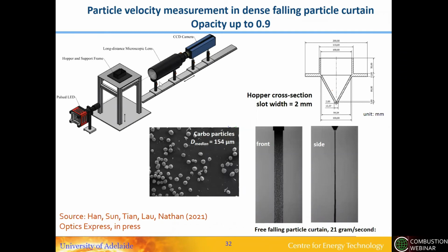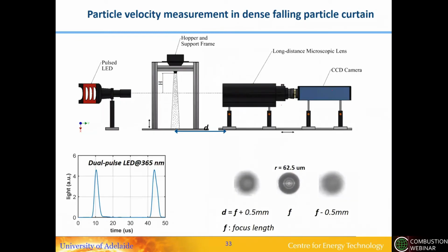As the light passes through this system, there's sufficient light even though there's a lot of attenuation. In fact, in some cases the opacity of this system is higher than 90%, and even significantly higher than that. As the light passes through, the key optical component, which is used to give discrimination in the line of sight, is a long-distance microscopic lens. It has a very narrow depth of field. This means particles that are slightly in front of or behind the focal plane will become blurred, and hence by doing some gradient processing of the image, you can remove the particles that are not in the focal plane. This gives you discrimination of what's not in the optical focal plane, which gives you the spatial resolution that's needed.